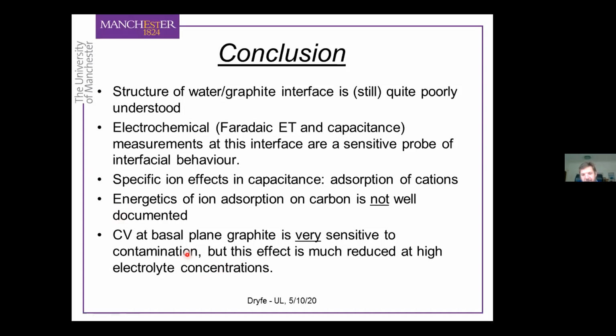And just another point to make is that these highly concentrated aqueous electrolyte solutions behave in quite unexpected ways, and particularly, although graphite becomes, as I've tried to emphasize, rapidly contaminated, and the electrochemical response of graphite is very sensitive to this contamination in aqueous solutions, working at these highly concentrated solutions really stops this contamination. So something completely different is happening at these interfaces when you have a high salt concentration.